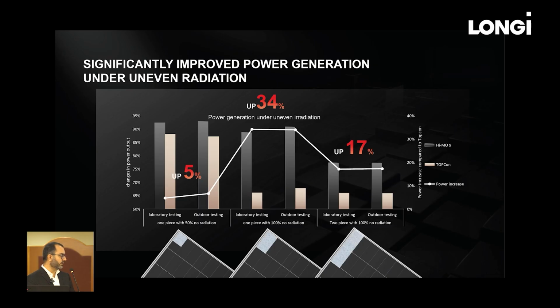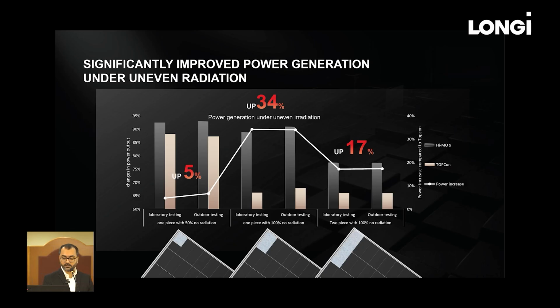So we did this experiment where we covered one cell up to 50%. We saw a 5% gap between Hi-MO 9 and TOPCon. Then we covered the whole cell, and the jump you can see is 34%. And then we covered two cells, and still we are managing 17%. So this shows, and in the coming video I will highlight, how efficient Hi-MO 9 is in terms of low irradiation and uneven radiation.